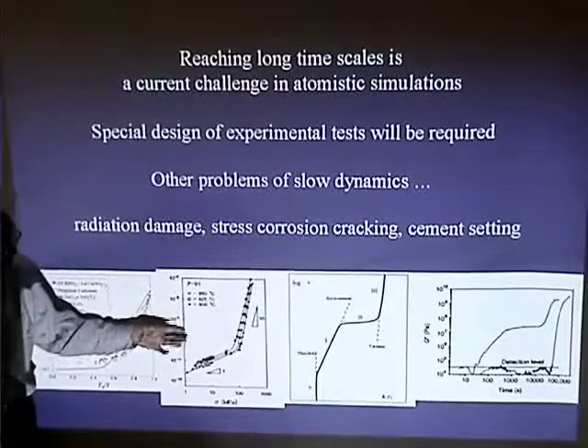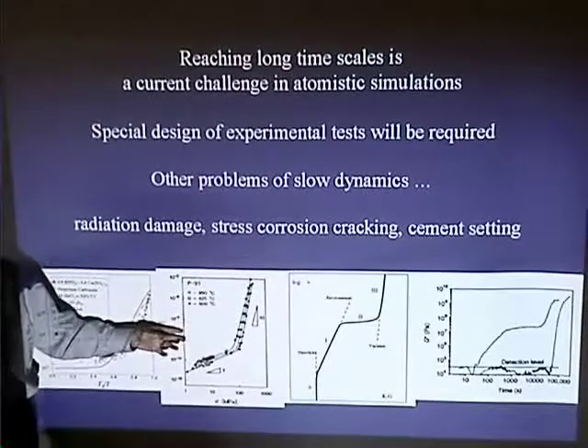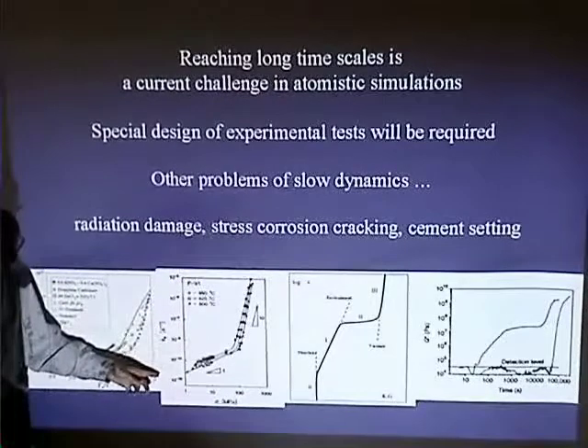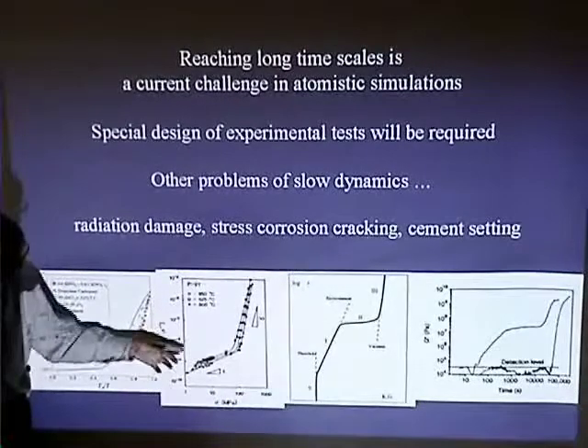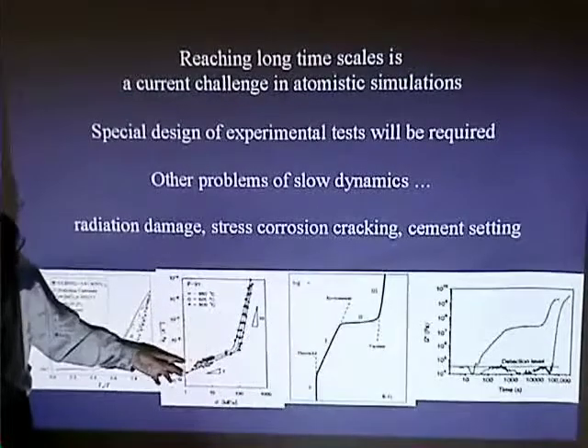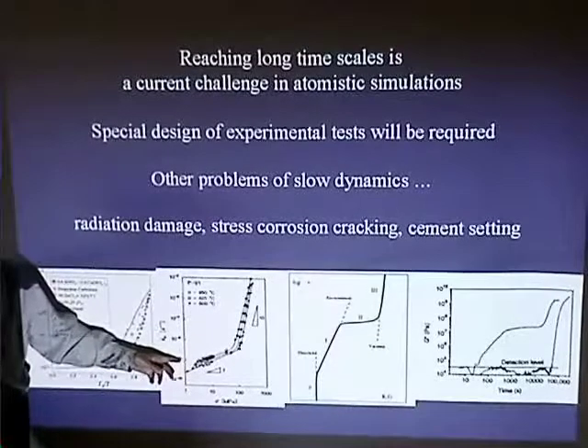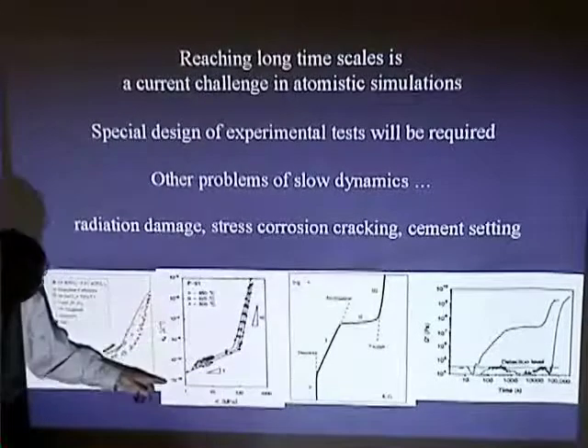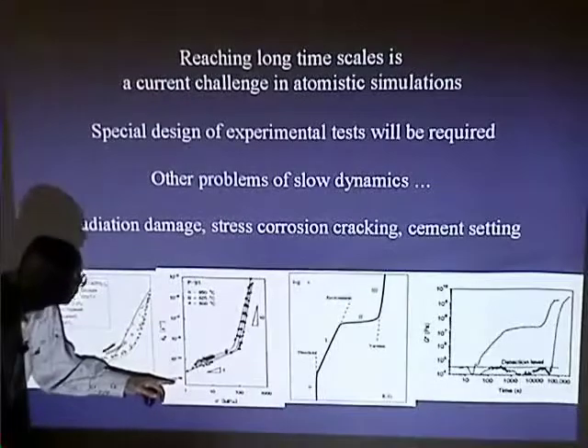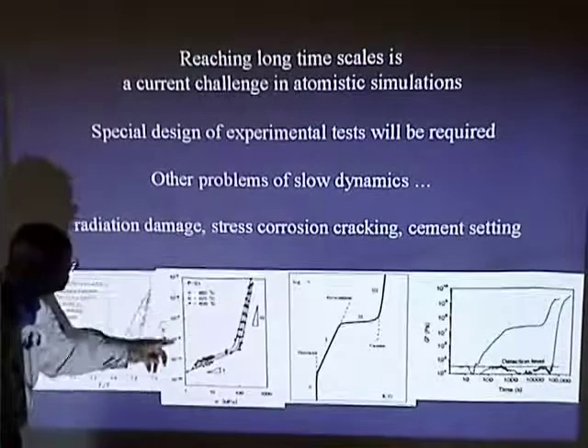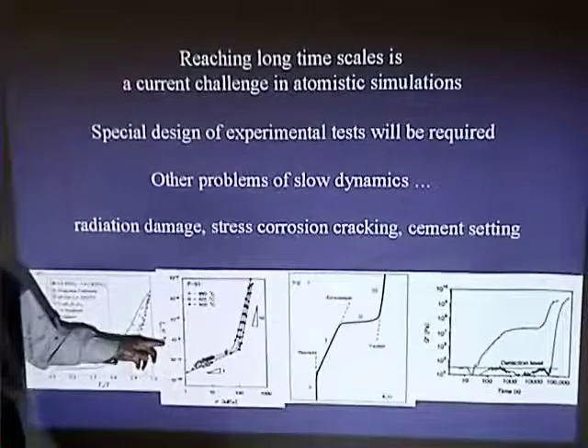In creep, for example, this is the creep curve, thermal creep in steel. What people find is that these are experimental measurements of creep rate. And the creep rate can also go from 10 to the minus 13 to 10 to the minus 3. So again, 10 orders of magnitude.